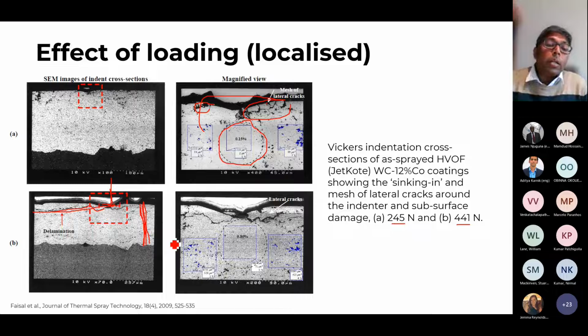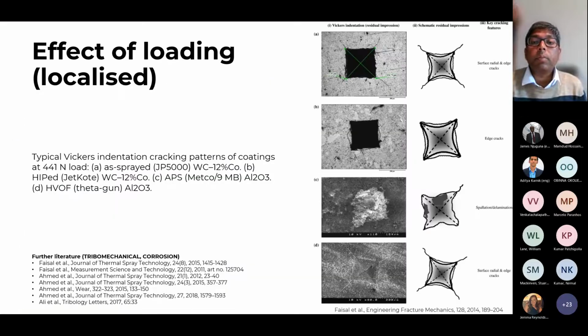So again, the thickness, the porosity, all these things will influence, meaning the process parameters you select to manufacture those are important. So most of the people who work in this area try to optimize the process parameters for enhanced behavior. Now, here, what we did, we selected different material, a different way of manufacturing it, and using the same load to do the Vickers indentation. You can see the fracture is very different. So it depends on the material on which you are indenting.